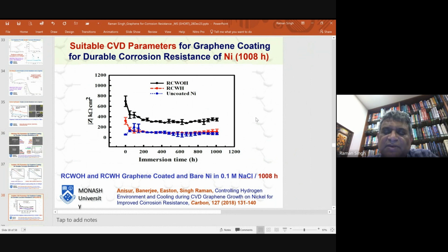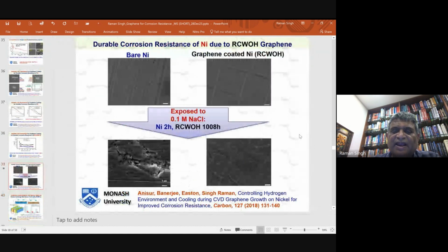And there is no reason why this will not last forever. Why I'm making that statement is simply because the deterioration in corrosion resistance can only happen if coating deteriorated, and my coating will not deteriorate. It is inert. It will not be chemically attacked. It is impermeable for the reasons that I showed you earlier, and also it is tough. It will not get mechanically damaged because it is tough. But if you impacted it, if you broke it, then there is a dangerous situation. But if the coating sustained, then it will be everlasting. It will not be undergoing much of chemical damage. And this you have seen earlier, bare nickel undergoes corrosion even in 2 hours. This is after 2 hours, but graphene coated nickel, even after 1,000 hours in this corrosive solution, does not show much of corrosion. It was recently published.